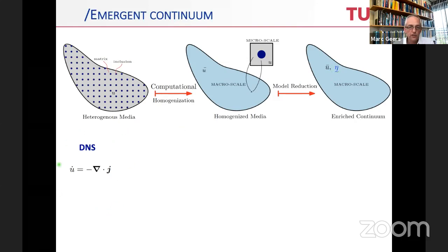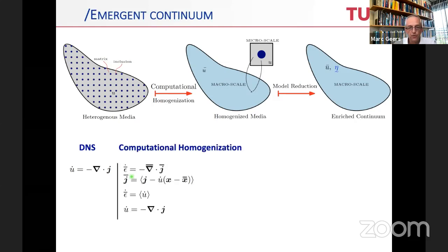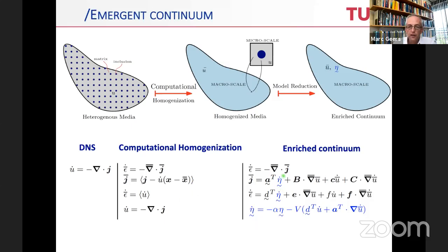The governing equation for the DNS problem is very simple. It's just the mass transport equation. Computational homogenization needs, of course, the downscaling and upscaling equations as well. And then the enriched continuum gives you coupling terms in which the eta fields are involved in the constitutive equations for the fluxes and for the epsilons. And of course, evolution equations for the etas, as was the case for the thermal problem and for the dynamics problem. So I think you can well recognize that the internal dynamics, the thermal problem, and the diffusional problem are all solved in the same way. And it gives rise to an enriched continuum in which the etas play the role of the amplitudes of the corresponding modes, be it dynamic, thermal, or diffusional.